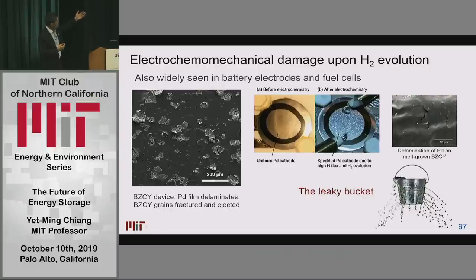Electrochemically, we cause fracture. On the left here, on a piece of electrolyte, is a thin film of palladium. And you see all these eruptions. Locally, we're creating very high equivalent pressures, and it's actually blowing the material apart. So this is the problem that we had to solve in order to try to maximize the amount of hydrogen we can get into palladium.